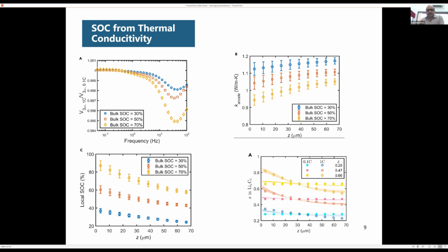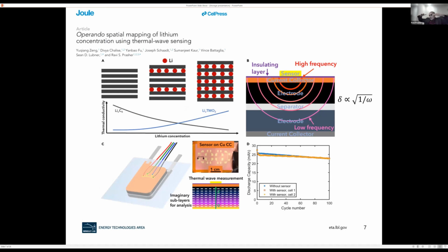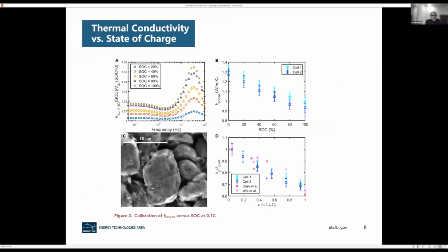You have shown the dependency on the frequency, that the penetration depth is inversely proportional to it. Are there any other factors? Oh yes, absolutely. This was just to explain the physics, but you basically solve the whole transient heat conduction equation for a sinusoidal heat source. Then you're fitting a model through the data that comes as a function of frequency sweep. Look at this, we are going almost 3 orders of magnitude in frequency sweep, so the penetration depth is changing with a huge margin, right? But you have to fit a whole thermal model through it to extract all the information out.